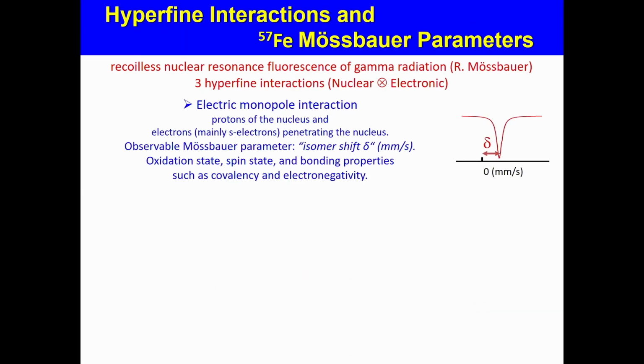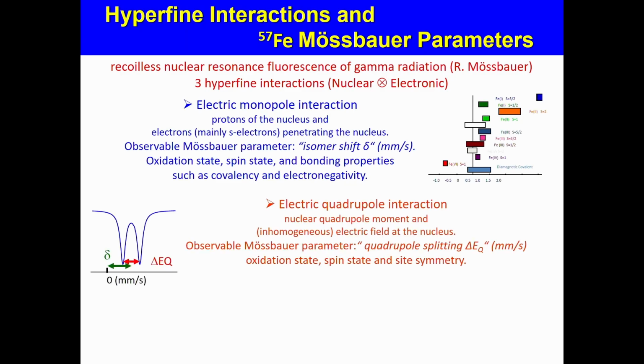To shorten again: with the electric monopolar interaction, you are sensitive to valency state and spin state. With the electric quadrupolar interaction, you can detect the symmetry of charges, or better said, the asymmetry of charges. But you cannot correlate directly: if this splitting is larger than that splitting, it is more asymmetric, but how much is difficult to say. But it is totally related to your question.